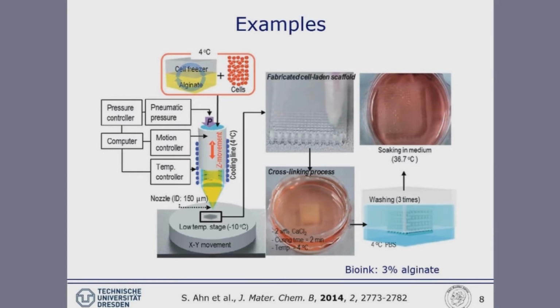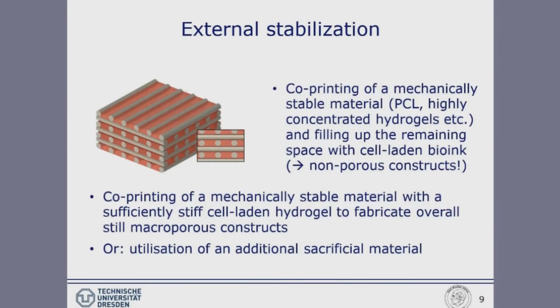A limitation, of course, is here that the heat transfer gets slower and slower the more layers you are printing on top of the cooled stage. This probably is made of metal, therefore has a good heat transfer rate. But the more layers are printed, the slower the cold is transferred to the next layer. And therefore, this is a nice option, but maybe not the way to go if you really want to have truly macroscopic, so centimeter-sized, cell-laden scaffolds.